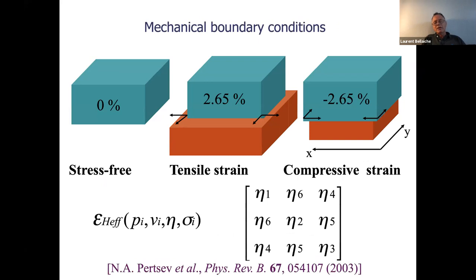What you have to do, you look at the strain tensor, and for instance, you fix eta one and eta two, that are basically the strain in the XY plane, and you fix them such as to reproduce the lattice constant of a substrate. You also fix eta six. If it's a cubic substrate, A and B are going to be perpendicular to each other, which means that eta six will be zero. And that's how you mimic your strain there.